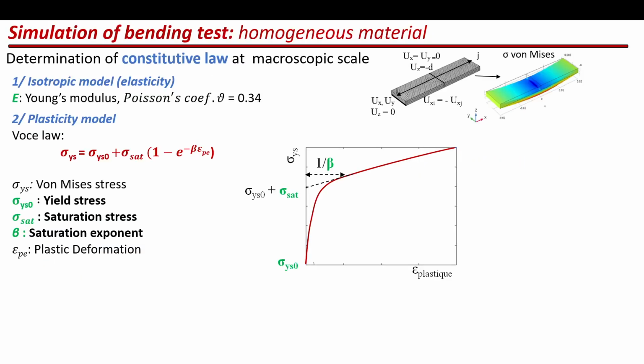So this is a kind of sketch of the scheme of the FE simulation. We use an isotropic elastic model, for which you need only Young's modulus and Poisson coefficients for the phases, but also, in order to account for the plasticity of the composites, we use the Voce law, which is only determined by three main parameters: the yield stress, the saturation stress, and the saturation exponent.